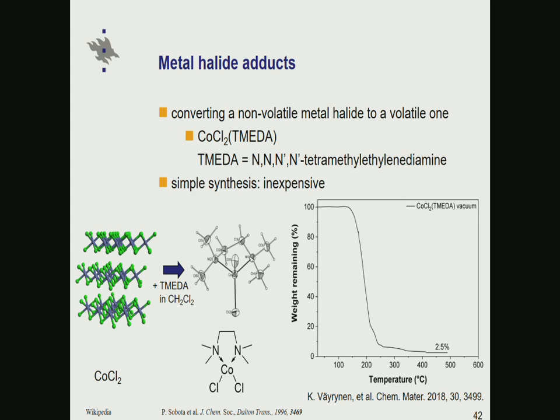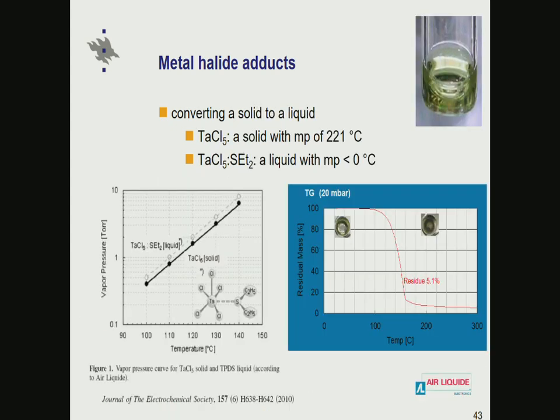But now, adding a neutral ligand, which is this kind of a tetramethyl diamine shown here, one is able to break the cobalt dichloride structure and make monomeric units. And because these are monomers, they are volatile. They show reasonably nice behavior in TG, and we could deposit cobalt oxides using this kind of metal halide adducts. And I'm sure there is lots of room also for developing corresponding systems for many other metal halides, which in general are considered non-volatile.